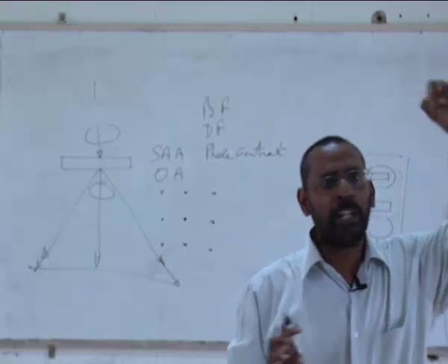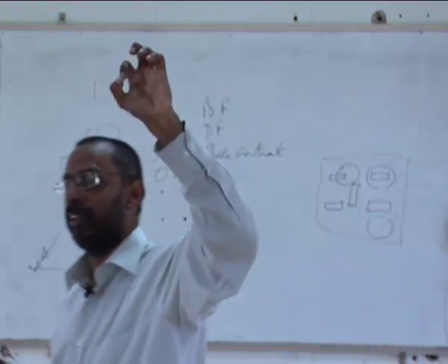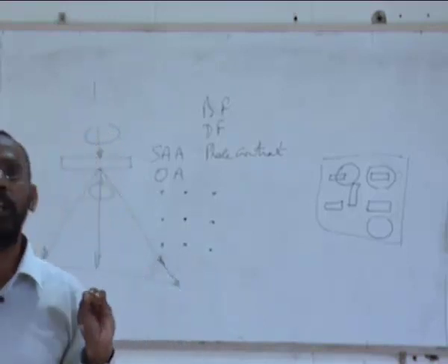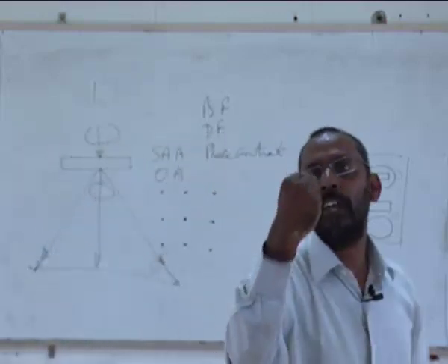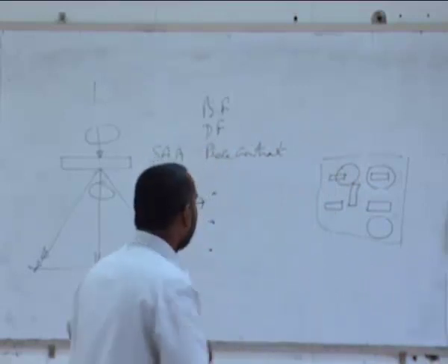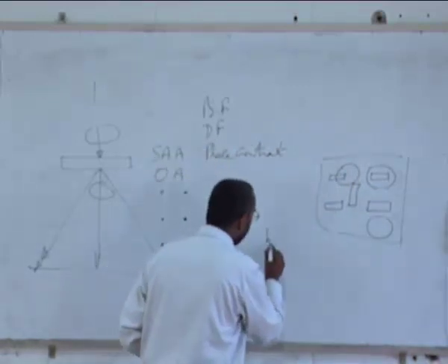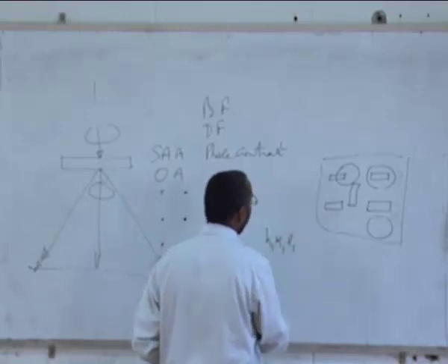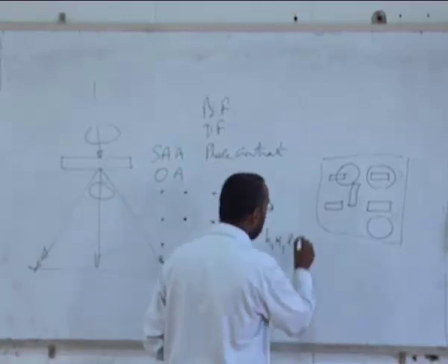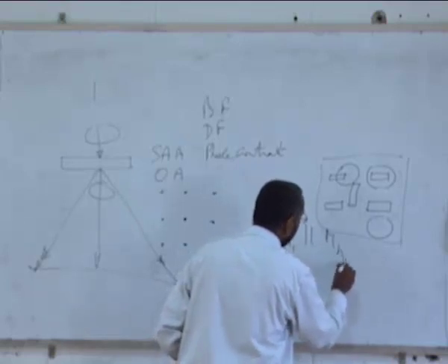So that particular diffraction spot, where there is exactly overlapping of the diffraction spot of the matrix diffraction pattern and the precipitate diffraction pattern, if I can find out the HKL of it, then I can say that so and so H1 K1 L1 of the precipitate is parallel to so and so H1 K1 L1 of the matrix.